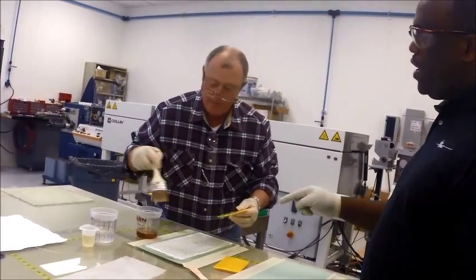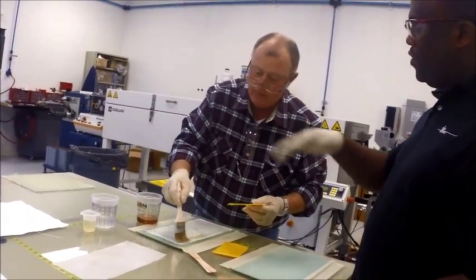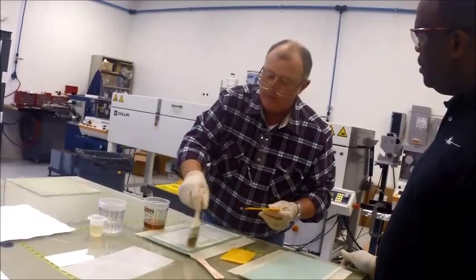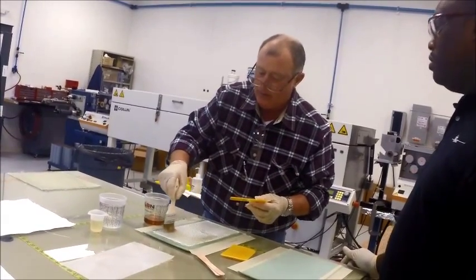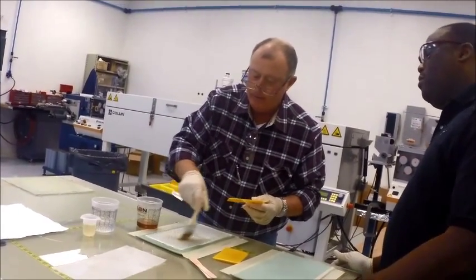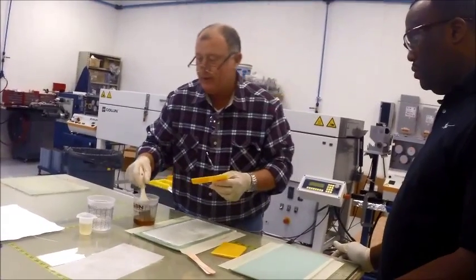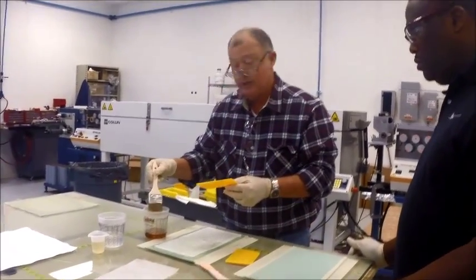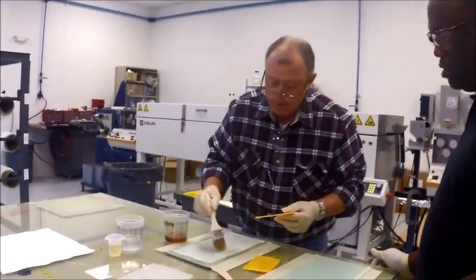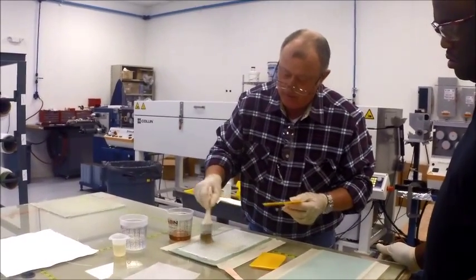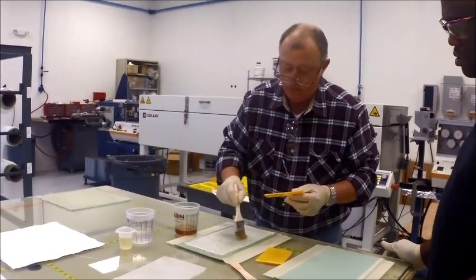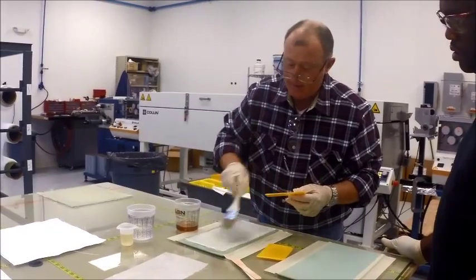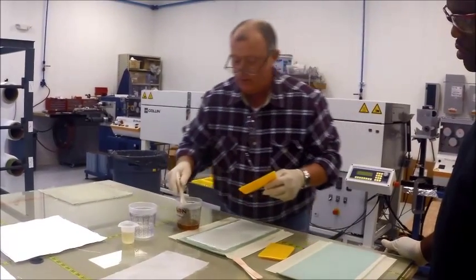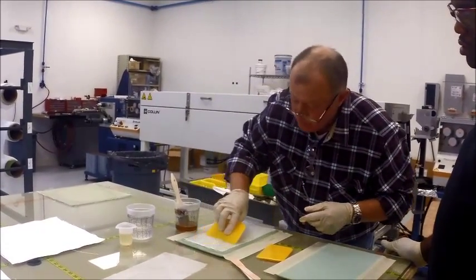You just call this one wet out, but you call that one a flood coat when you leave an excessive level on the top there. And that's typically what you'll see on stand-up paddleboards or surfboards, where they'll come back and flood coat the top. What that does is it tends to fill in all the little micro voids in the laminate and gives them a little nicer surface for which to abrade.